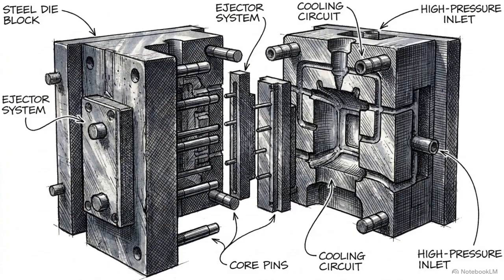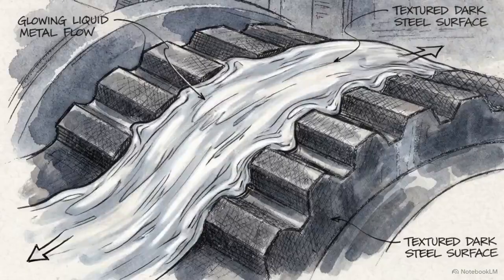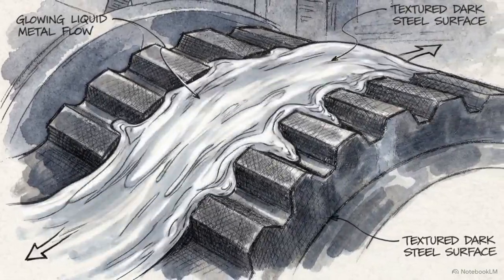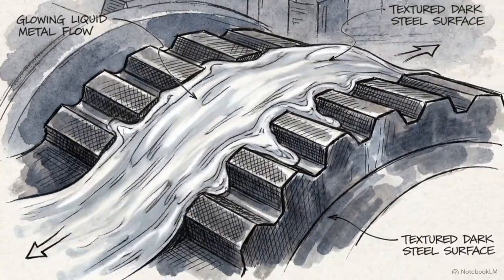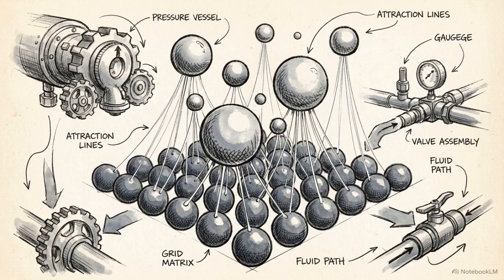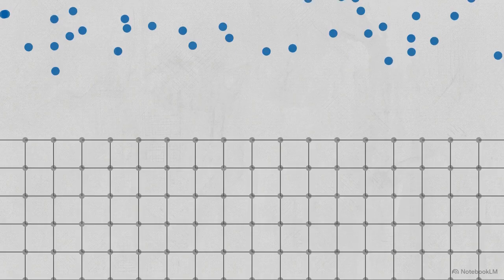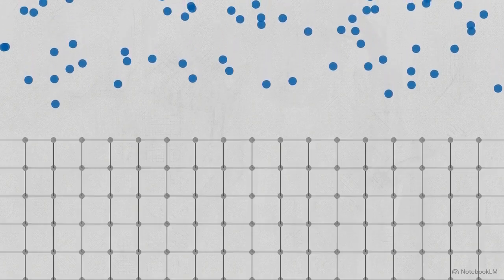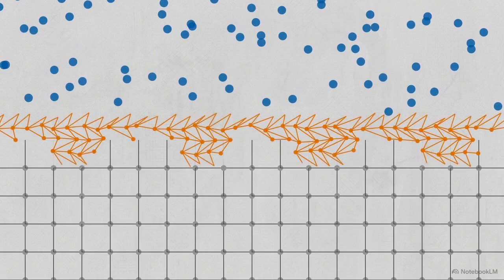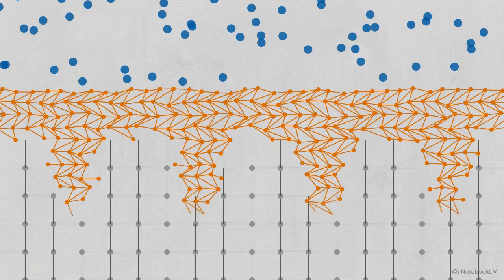If we zoom away from the factory floor down to the microscopic interface, we can see exactly what happens where the hyperheated liquid aluminum makes contact with the hardened steel die surface. In its molten phase, aluminum is highly reactive. It actively seeks out other elements to form stable chemical bonds. When that liquid aluminum presses directly against the rigid iron matrix of the steel tool, the conditions for a reaction are set. The two distinct metals immediately begin to fuse, reacting to form an entirely new layer at the boundary, an aluminum-iron intermetallic compound. This new intermetallic layer is exceptionally hard. It acts as an unbreakable metallurgical anchor, locking the casting directly to the die.